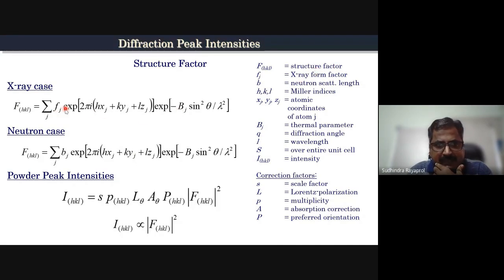Okay, and this is the equation which has the position, XYZ position, of the atom. HKL values are the planes from which the particular atom reflects, or the Miller indices, because of the reflection coming from those particular sets of positions of atoms. Bj is the thermal parameter. Sin square theta or sin theta by lambda is actually the scattering function which we are using. In case of neutrons, this is called the neutron scattering length, bj, and most of the equation remains the same. So the procedure for X-rays and neutrons are not much different except for some minor changes.